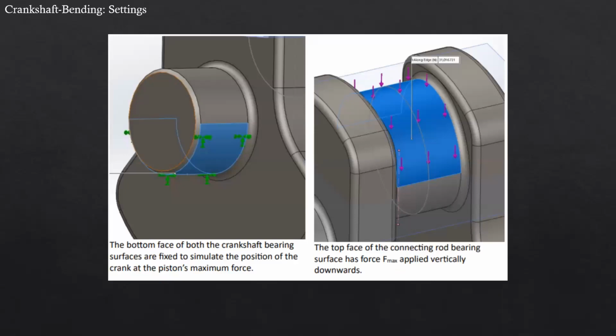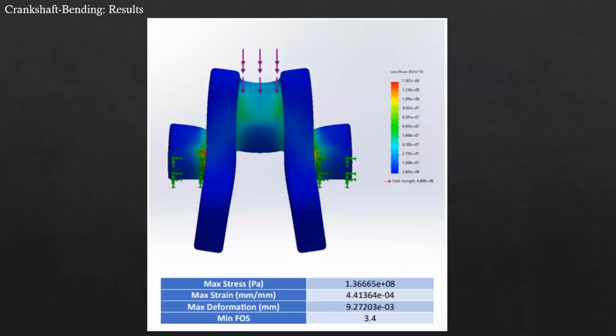Moving on to the bending of the crankshaft, we chose a 4130 steel that was annealed at 865 degrees Celsius. You can see here where we went ahead and did our fixturing on the top face of the connecting rod bearing and the bottom face of the crankshaft bearing. We ended up with a minimum factor of safety of 3.4, which means that we are well in line with not having any limits within the design. We could potentially reduce material from the crankshaft to lower our factor of safety, to increase responsiveness from the motor and